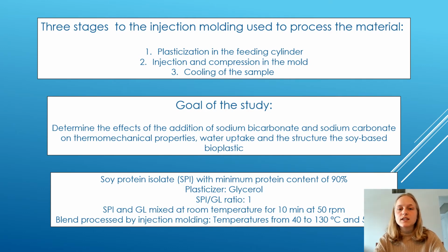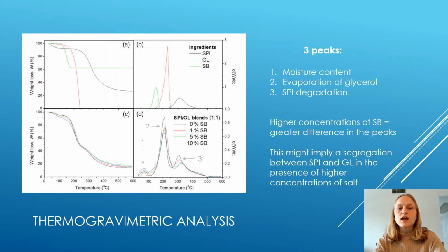Soy protein isolate with a minimum of 90% protein content was used with glycerol as a plasticizer. The SPI-GL ratio was 1, and they were mixed at room temperature and 50 RPM for 10 minutes. The resulting blend was then processed by injection molding at temperatures varying from 40 to 130 degrees Celsius and at 500 bar pressure. To begin, a thermogravimetric analysis was done.